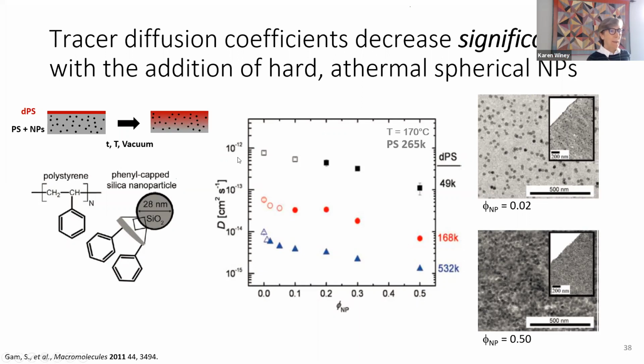We can see that the diffusion coefficient without nanoparticles and then with more and more nanoparticles decreases, and for all these different molecular weights. So polymers are moving slower. Even when the concentration of nanoparticles is quite low, we're still getting a significant drop in the diffusion coefficient. And by the time we're out to 50% nanoparticle concentration or so, we've dropped by an order of magnitude.